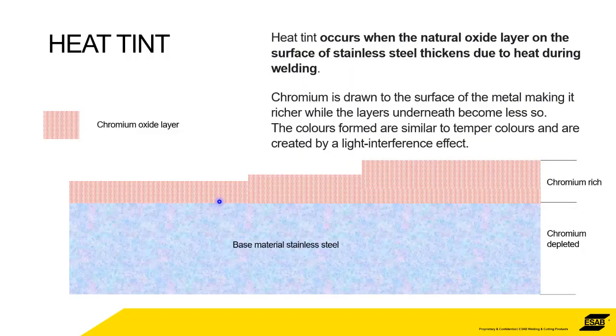I mentioned it before that it occurs when you get the chromium-rich chromium oxides on the surface, and as you heat up the base material, so we're talking the heat affected zone that gets to very high temperatures. The higher the temperature causes the chromium, the chrome, to get drawn to the surface and come out as chromium oxide, and it gets thicker and thicker, and the thicker the layers, then the darker the tint is. The one thing that has to be taken into consideration is that obviously all this chrome's appearing on the surface, and it's not for nothing. The chrome's coming out of the base material.